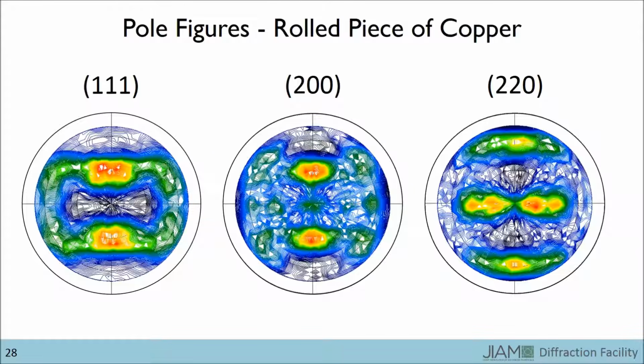We are not limited to only investigating one type of plane. If we were to rotate the source and detector to the angles that should produce other planes, we can do the same experiment and determine each plane's preferred orientation. For this cold-rolled copper example, I also tested the 200 and 220 planes. Depending upon your material, you could get very different looking pole figures.